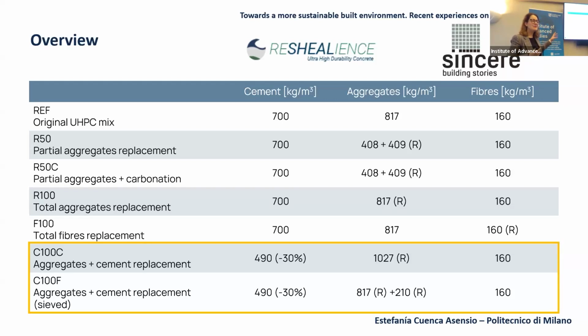And that's interesting because here we are recycling ultra-high fibrous concrete. So our question was, is it possible to produce a new ultra-high fibrous concrete, but more sustainable, by recycling the former one? Okay, so it was possible. Another thing is that we replace not only the cement, but also the aggregate. As you can see, the R means that it's recycled. So in the first one, we have a mix in which all the coarse aggregates were completely replaced.